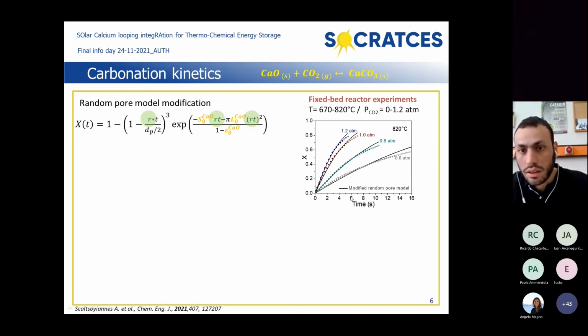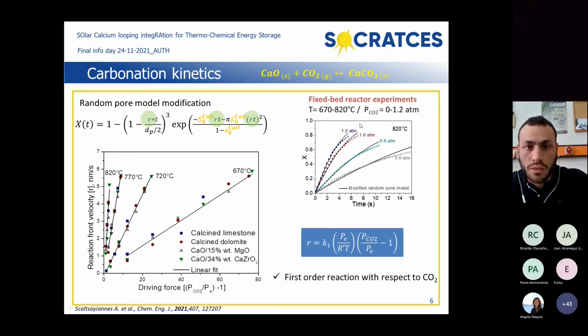It's very important to highlight here how fast this reaction is. Carbonation achieves around 60% of conversion under these conditions in only a few seconds. And after fitting this equation to the experimental curves, we derived this parameter R, the rate of carbonation. And here we have a first order reaction with respect to the CO2. And we can see that all the materials tested, we tested 4 sorbents with a different inert phase content, are fitted by the same fitting lines, which implies that the modification was done successfully.